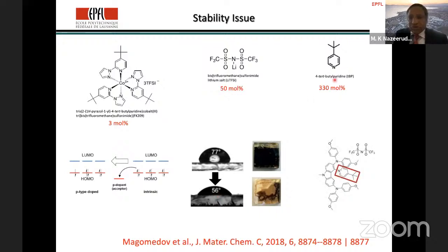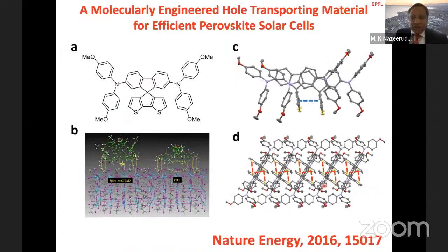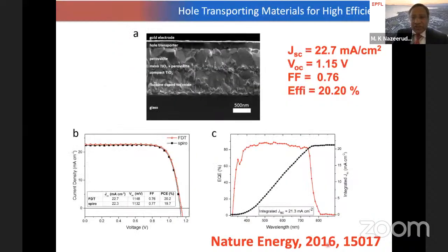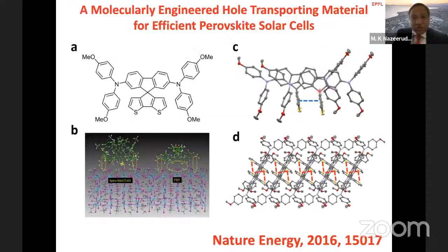Not only that, we have a pyridine, which is a strong base, which nucleophilically attacks one of the groups of the hole transporting material. So to avoid all this, we have developed a new hole transporting material based on thiophene, shown here, and this was published in 2016. The efficiency is not very high, around 20%,